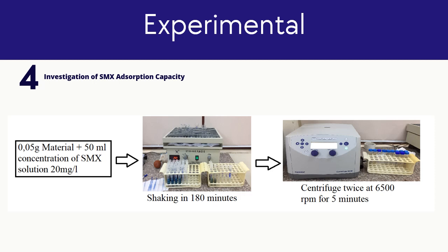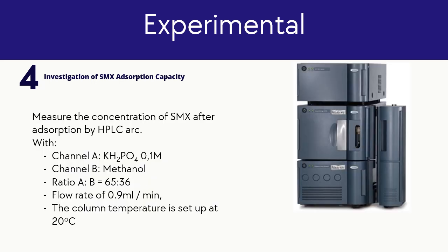After the absorption period, the sample was centrifuged at 6,500 rpm for 5 minutes, and the upper part of the solution was extracted for concentration determination using high performance liquid chromatography, HPLC.